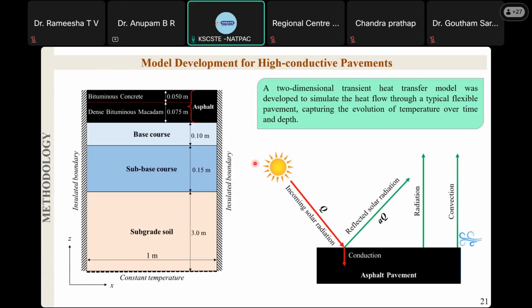So is it within the layer or on the surface? Actually, within the layer, inside the layer. Practically, when we are constructing this bituminous layer, we have to mix this material with the mix. Either we can modify the bitumen used for that, graphene modified bitumen or graphite modified bitumen, or we can add some materials. For example, we can use steel slag, which has higher thermal conductivity than normal aggregate. Such materials we can use during the mixing stage. We have to add higher conductivity material during the mixing stage, or modify the binder with higher thermal conductivity material and use that for the construction.